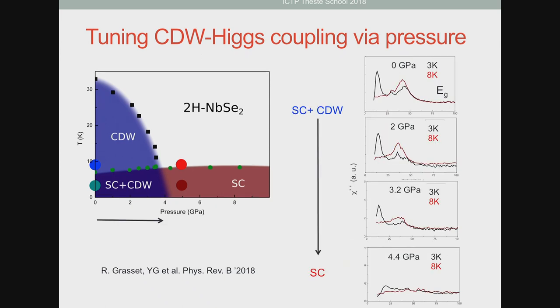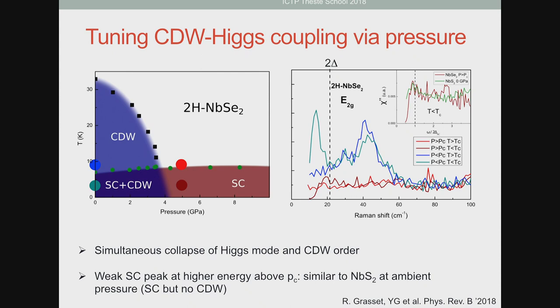Now, what happens when you cool down through TC? This is above and below TC at selected pressures. What you see is that up to 3.2 GPa, you still have the emergence of this relatively sharp peak at low frequency in the superconducting state. There is still a transfer of spectral weight. Once you move out of the coexistence between superconductivity and charge density wave, at 4.4 GPa, instead of a relatively sharp peak, you have a broader signal. Importantly, and I'm going to show you that in the next slide, this signal is located at a higher energy.